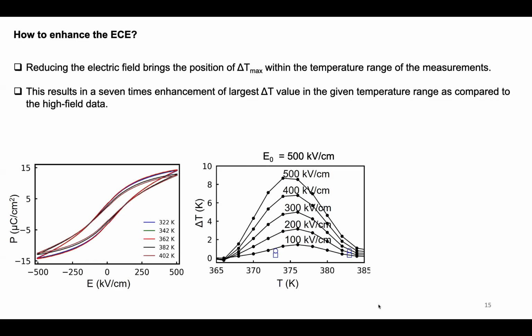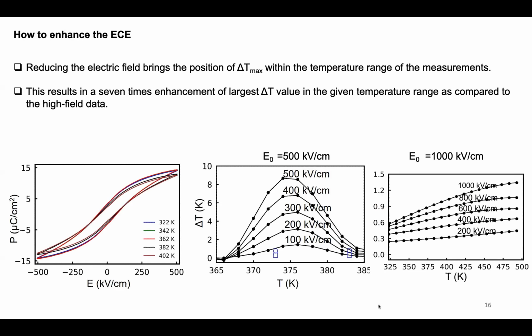So what we do is decrease the poling field. By doing that, and this is again experimental data, not from the simulations, once we decrease the field, there is a shifting of the peak to the desired temperature range, and because of that, there is an enhancement of the change in the temperature, of course, because the field is now not very large, but a reasonable amount. When I compare with the largest field that we applied, it makes sense here, because you can see the largest field has suppressed the data, and the lowest one is not too low, but a medium range of field will give us the maximum change in the temperature.